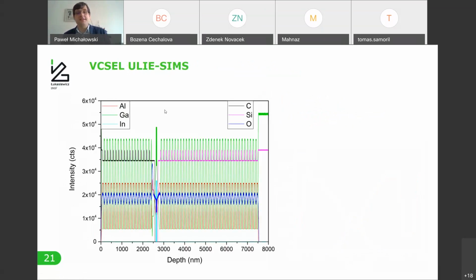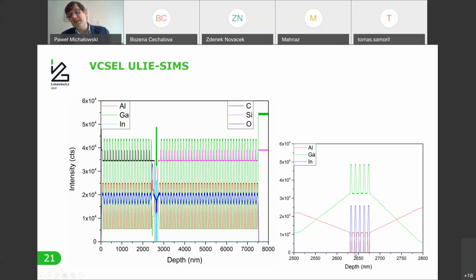And then finally, the result is presented here. So now, as you can see, this is a very high quality result. All the layers are represented with a very high precision. We can also include gallium signal here. We can also include the dopants and contaminations in oxygen. So we can see the carbon p-type dopant and n-type dopant. And we zoom in into the quantum well region. We can see a perfect separation of 5 quantum wells.